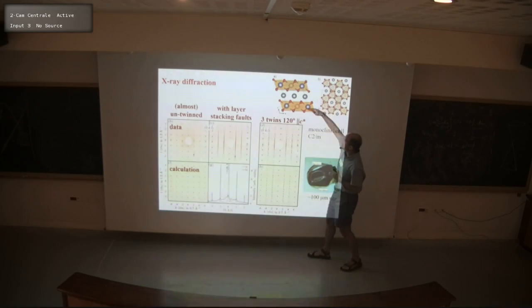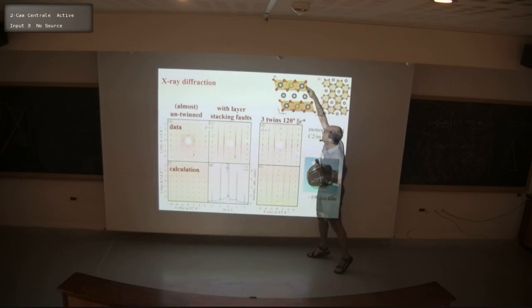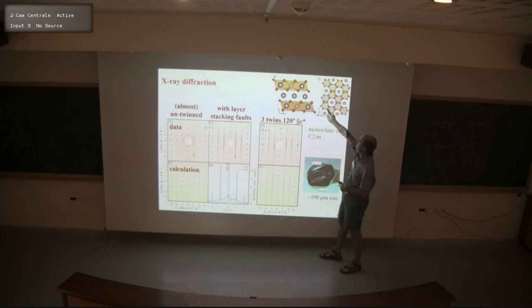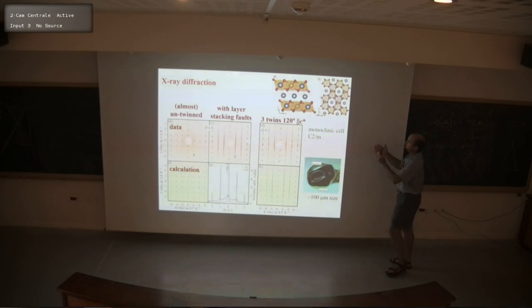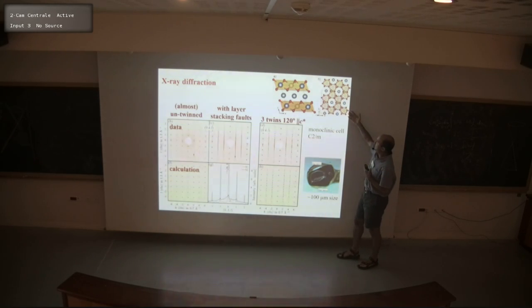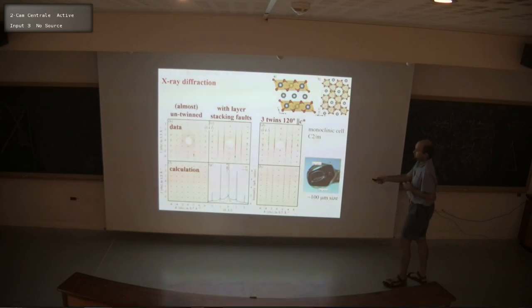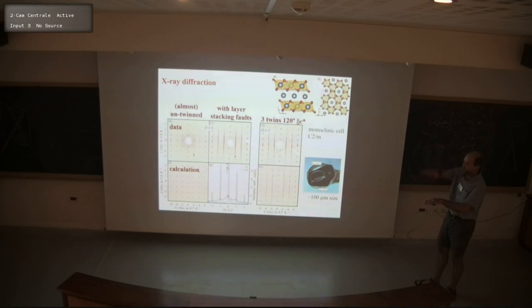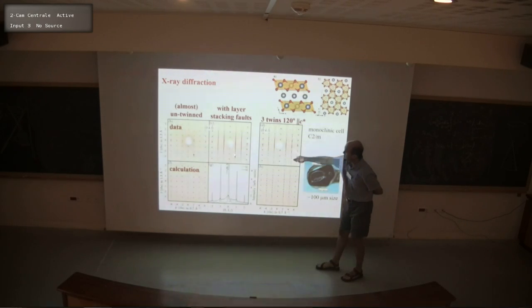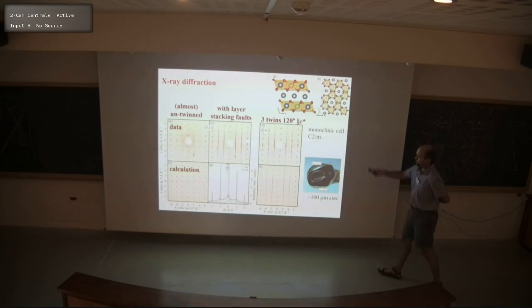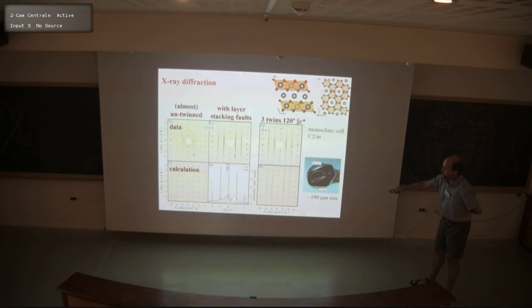It's only the interaction energy with the second layer which makes a difference if these are in register or not, which means that energetically, there's a very low cost to have stacking faults, random shifts of the center from here to there, and so on. And this diffraction pattern here illustrates that on a sample which has essentially no correlation between the layers, instead of Bragg peaks, we see very extended diffuse scattering along the disordered direction. So you can see this lower trace out here.